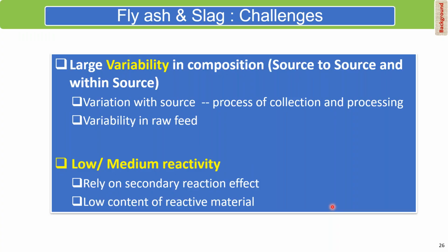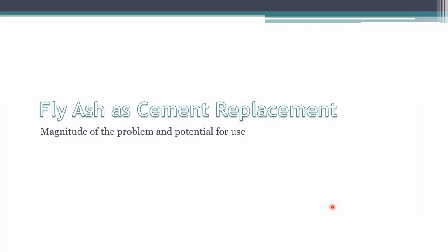So the challenge that we currently have with the larger use of fly ash and slag in concrete is a large variability in composition. Source to source, and within a source, batch to batch, there is large variation. And typically these are low to medium reactivity materials, and they rely on the secondary effect. This is not the primary reaction that we're looking at, but the secondary reaction. We're utilizing the lime that is produced by cement hydration to produce CSH.